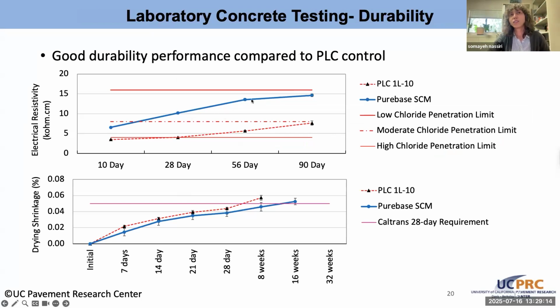Blue is our case material here. This is the result of electrical resistivity, bulk electrical resistivity, showing very good resistivity against the flow of electricity, electric charge through the sample, generally indicating that the pores are isolated and are not connected so that current can't flow through. But again, it is highly impacted by the ions that also come along with the material into the pore solution. So got to keep an eye on that.